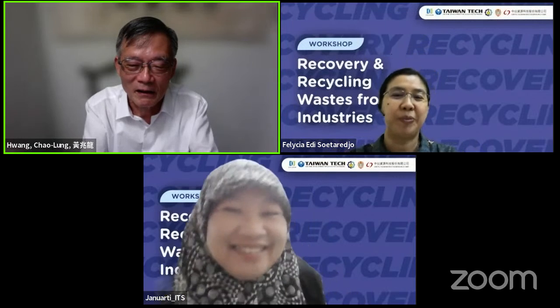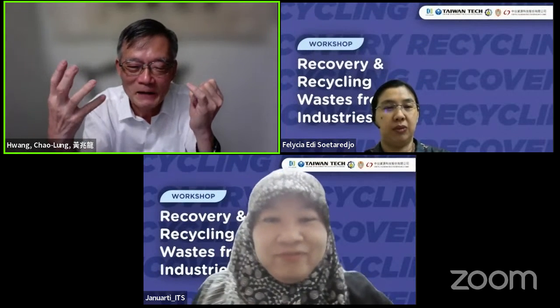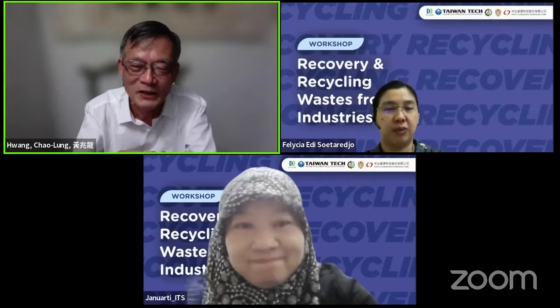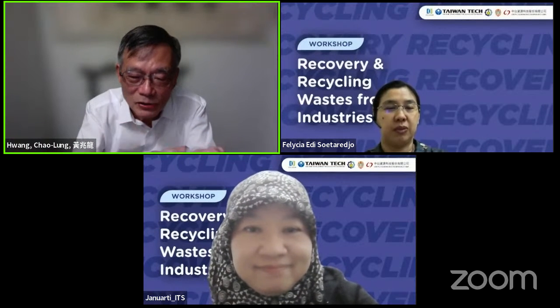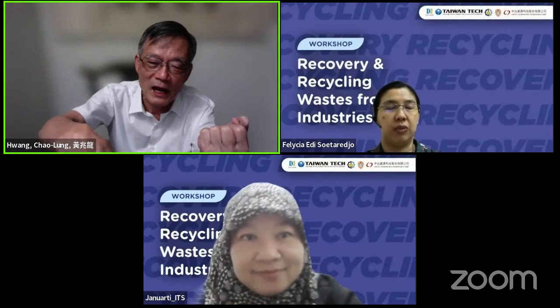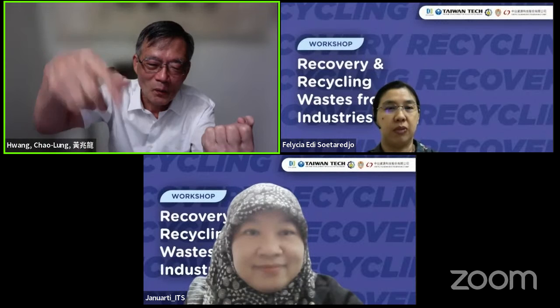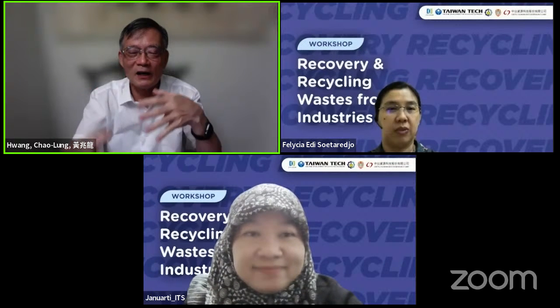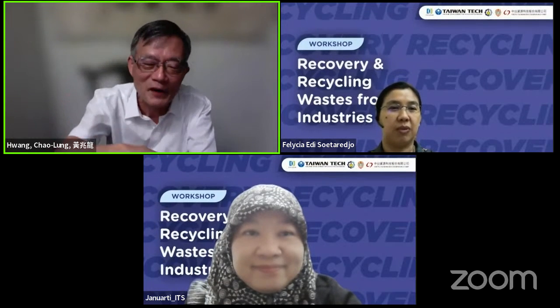You need to invest money to have a good machine. Without a good machine, you cannot produce very good concrete. In the machine I designed, actually in 80 seconds you can produce one batch, and continue pouring without stopping, you just continue. And then mass storage. I mentioned mass storage is another way to produce very good concrete. What is important is how you put in the water, just like ASTM 109 or ASTM 190, the blended mortar. The methods are quite the same because it is according to the hydration of cement. If you do it this way, the 5M, then you can produce very good concrete.